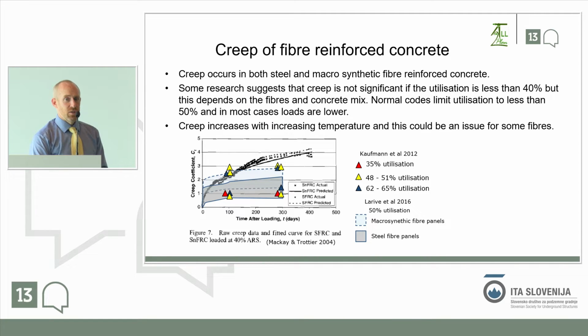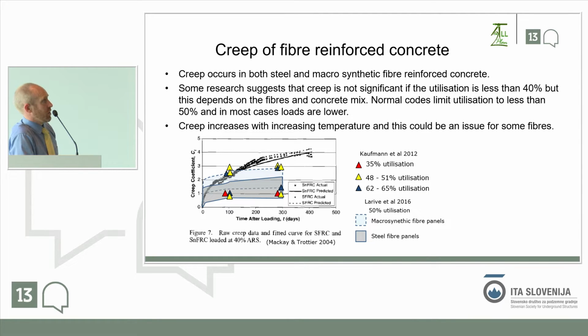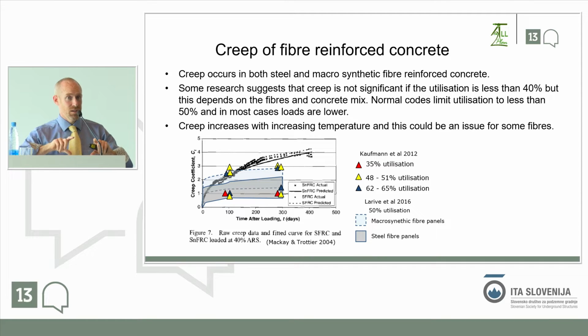Creep is a subject that crops up very often. I've had the privilege of sitting on some committees where we've looked at these things, and there's a lot of debate about this. So I'm going to present my best understanding of the data that we have. It's raised as an issue for macrosynthetic because, of course, it's a plastic, and we know that plastic creeps. What I'm plotting here is data from 3 different studies. This is time, and these are the results, the creep coefficient, which is measuring how much extra deformation you get if you take a beam, you crack it, and then you keep a load on it. And obviously, if it's creeping, it'll continue to move.